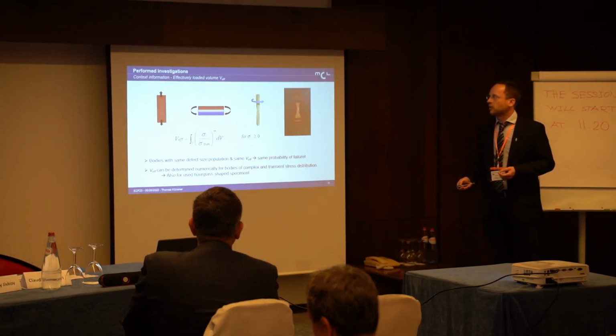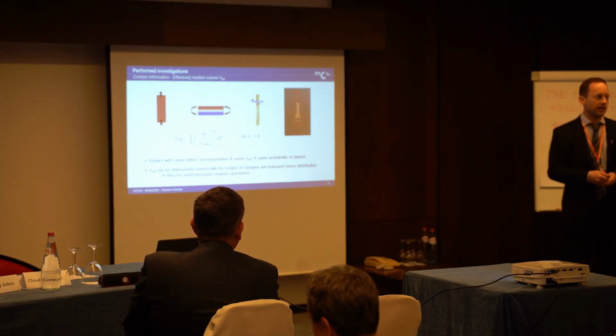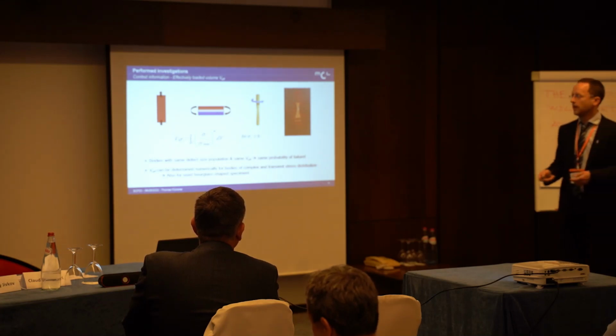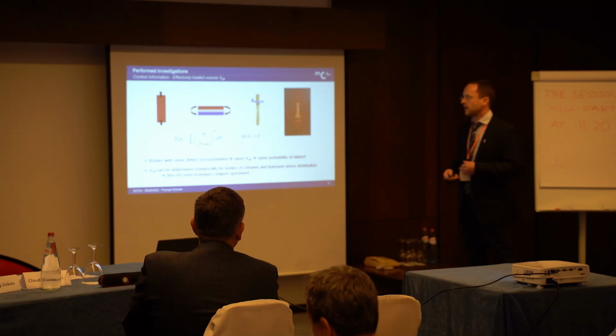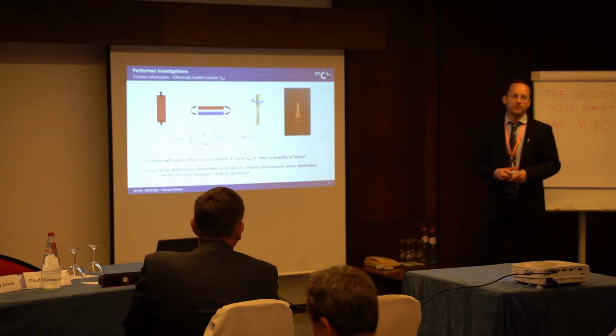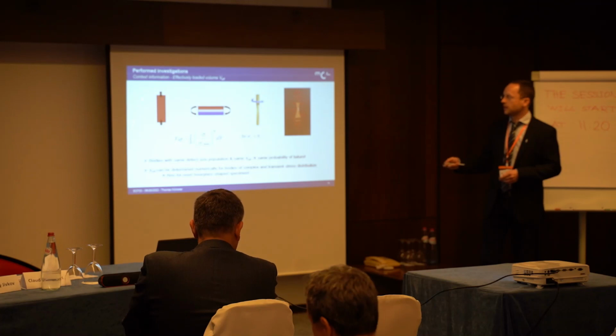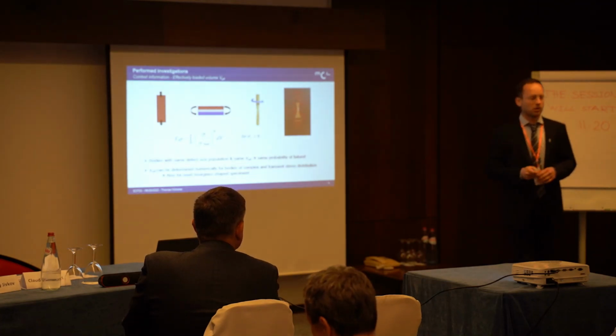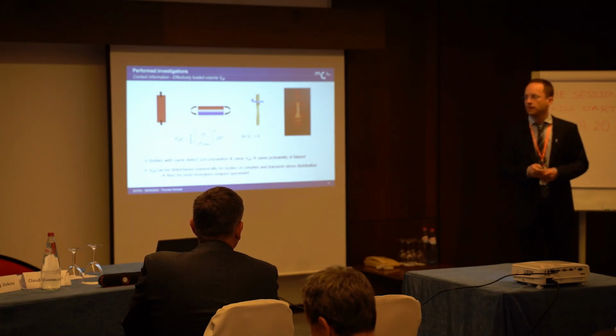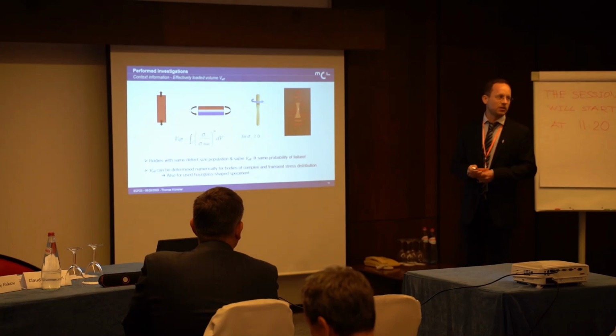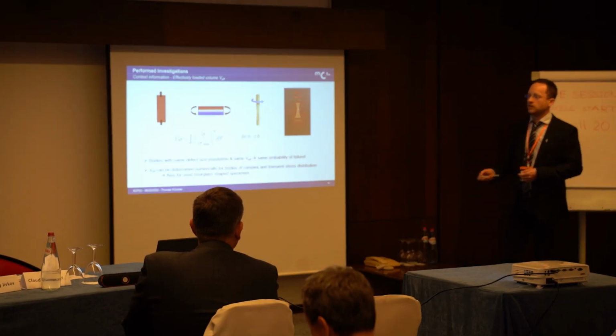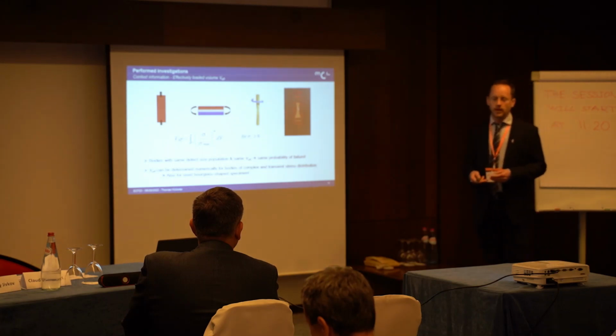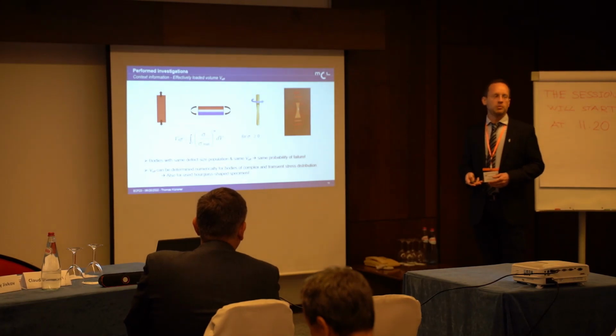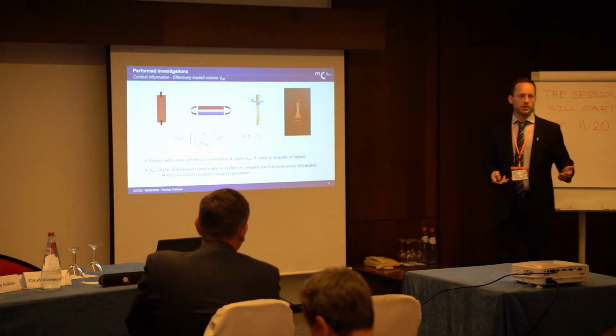What is this effectively loaded volume? It's a way to assess the failure probability of complexly loaded structures, because bodies of the same defect population and same VF show the same probability of failure. This VF can be determined analytically for very simple load cases, and for complexly loaded specimens that may even deform plastically during loading, you can evaluate it numerically. That's what we did. It's basically a weighted sum, so to say, of contributions to the probability of failure of a certain structure under arbitrary loading situations.